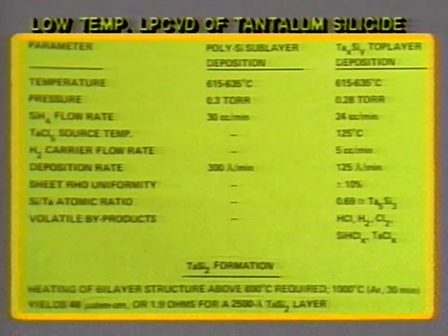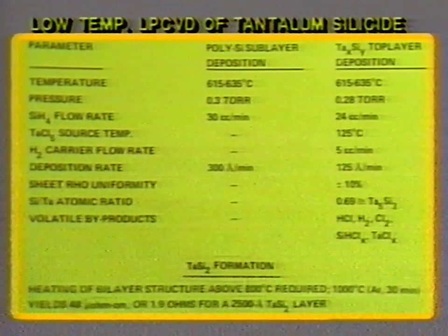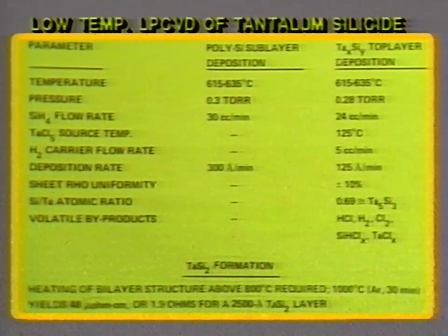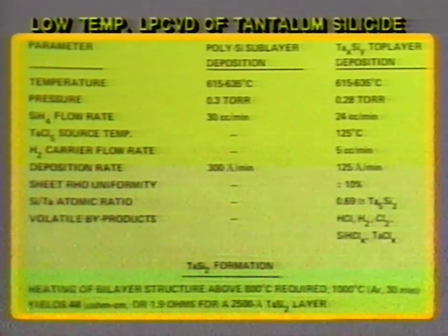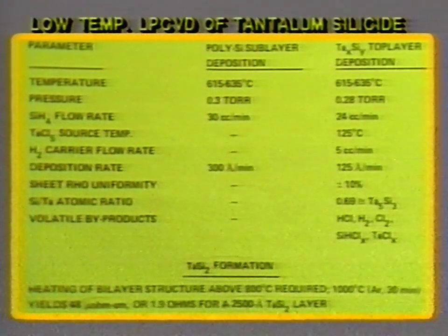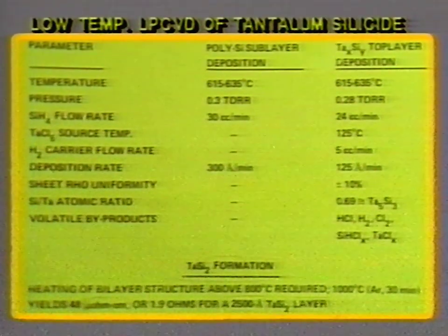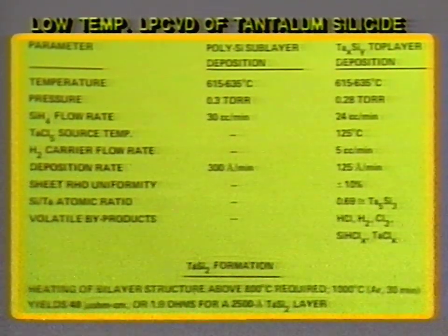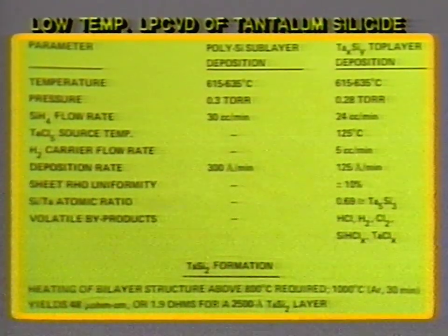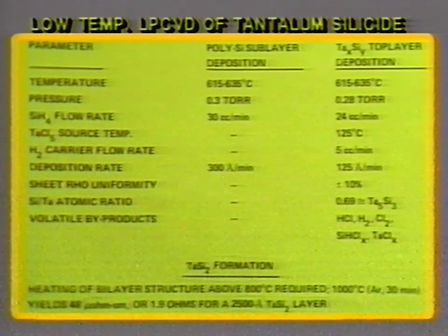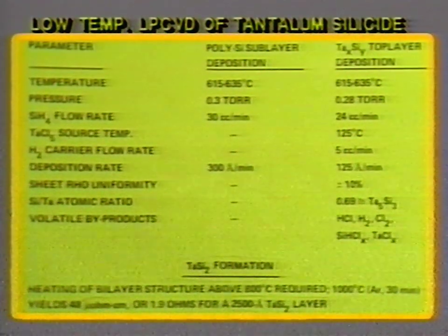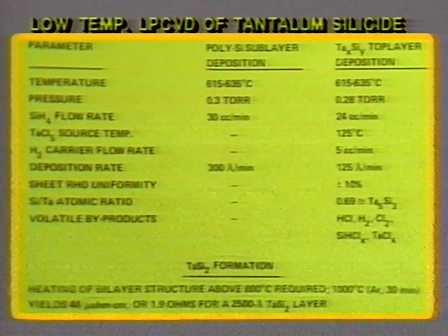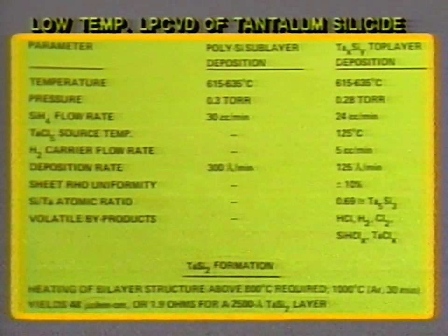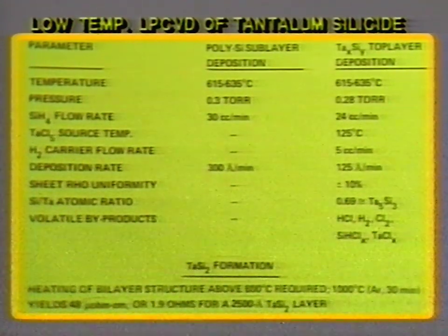Now, if we have a look at the tantalum silicide in the slide shown here, this is one way we can produce tantalum disilicide, namely the deposition of a polysilicon layer first at a temperature of, say, 615 to 635 degrees C to produce a polysilicon sublayer. The silane flow rate is also shown here, and some additional details.